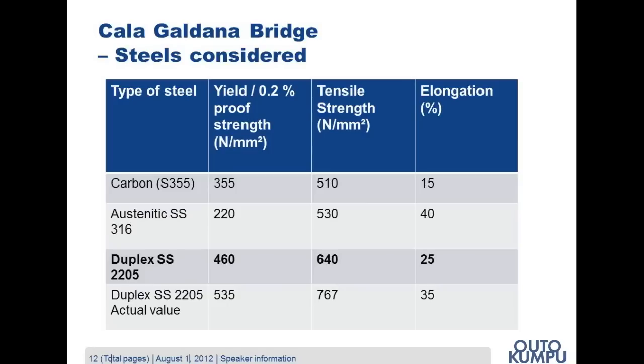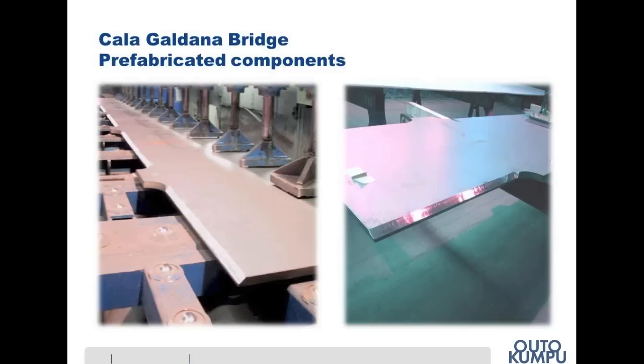The final choice became the duplex stainless steel grade 2205, with the minimum yield strength according to the standard of 460 megapascal. However, the actual values received were a lot higher. Other important criteria except the strength were corrosion resistance, low maintenance, and easy and quick assembly.